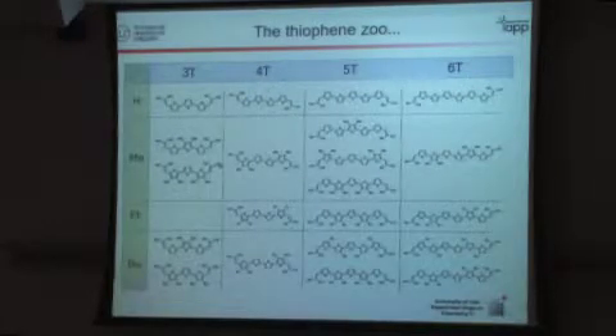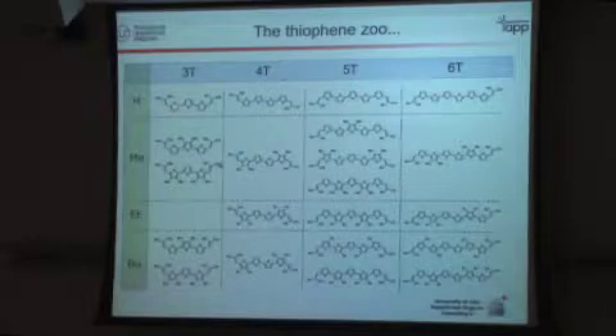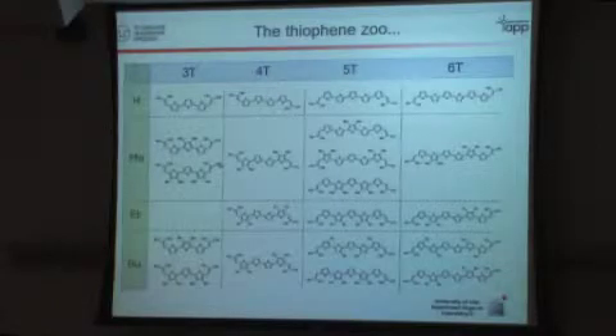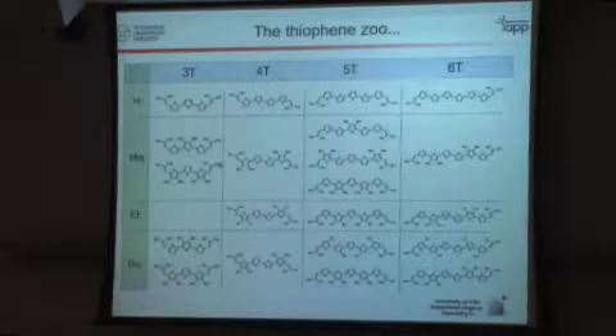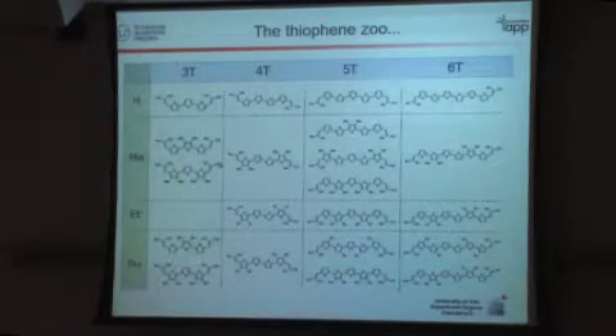The one handle is actually the backbone length in thiophene units. We typically look at 3 to 6. And the second handle now is the side groups of the molecule, either simply hydrogen or up to butyl groups. Now what are the effects? This handle actually changes directly the electronic properties of the molecule. This handle does not change the electronic properties, but it changes the crystal packing. But this way again, it changes the electronic properties in the solid state.